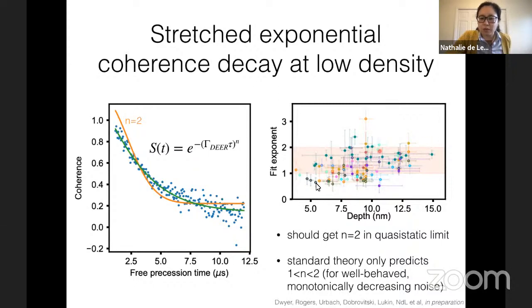And in general, you see this sort of depth dependence to your exponent. And also, much to our surprise, we saw a large number of exponents that were below 1. And you can write down a pretty simple argument that you should have a strict bound on this n between 1 and 2, as long as you have well-behaved and monotonically decreasing noise. Okay, so that's puzzle number 2, that we see these stretched exponents for our coherence decay.